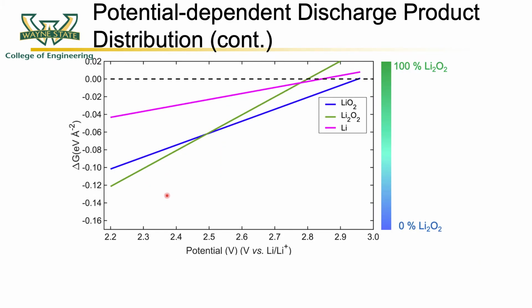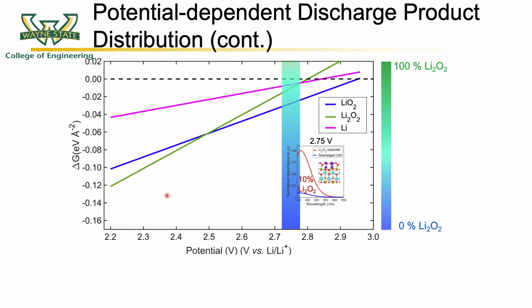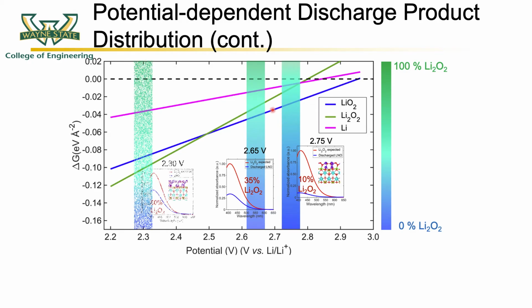In order to validate these theoretical calculations, we discharge the electrode at a constant potential of 2.75 volts and titrate the electrode to find that only 10% of the discharge species can be attributed to Li2O2, indicating 90% is due to the formation of LiO2. As the discharge potential is lowered to 2.65 volts, the amount of LiO2 decreases and the amount of Li2O2 increases, consistent with our phase diagram.